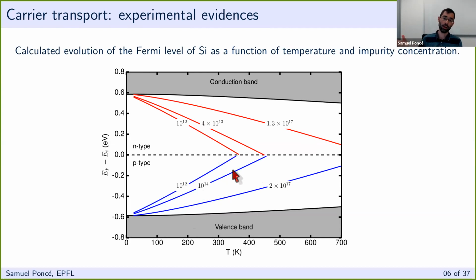What you can also notice is that those numbers are different, and this is simply because in silicon, the conduction band has 6 pockets along the gamma-X direction. And so when you're populating those 6 pockets, it's not the same as populating just the valence band. And so this is why you have this asymmetry.